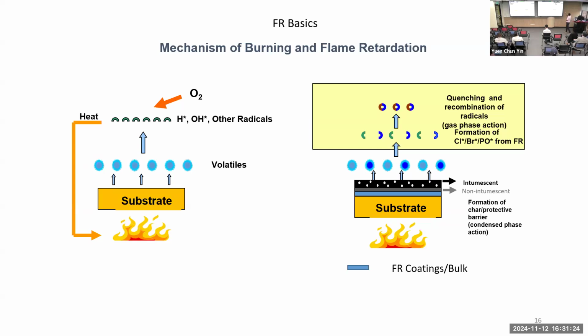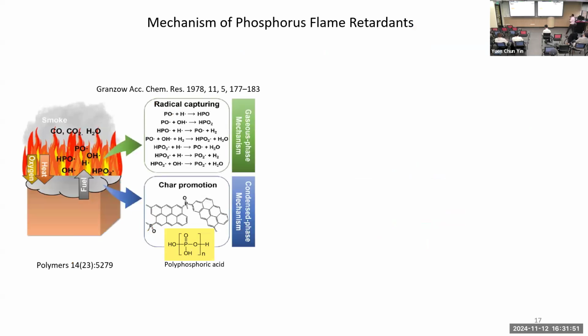So basically, halogenated flame retardants, phosphorus flame retardants also release radicals which can recombine hydrogen and hydroxyl radical, which are actually the main combustible component, which can be recombined to form water and prevent the burning process. So this is the basic mechanism. Phosphorus flame retardants can work in condensed phase and in gas phase. In condensed phase, they form this aromatic char, which forms a barrier on the surface. And in the gas phase, they form phosphorus oxide radical, which can then recombine hydrogen hydroxyl radicals. You can say it's a catalytic process. Okay, so this is something you have to know.